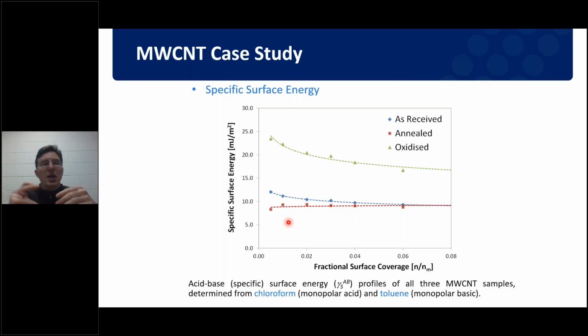So perhaps we have removed some polar impurities on that surface. Perhaps we've removed some of those oxygen-rich groups which were causing some of that polarity on the surface. So this has had a very measurable impact on not only how my polar probes are interacting, but also my non-polar probes. And I have a profile and heterogeneity associated with all different energy types.